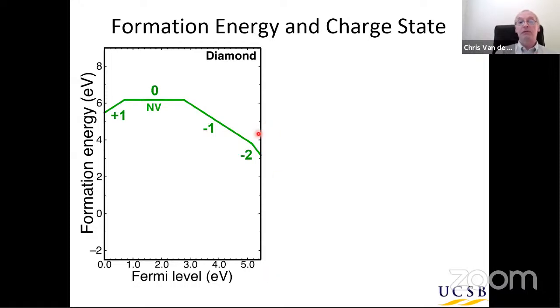And very often we use diagrams as the one illustrated here to investigate these issues. What is plotted here is the so-called formation energy of a defect, how much energy it costs to, for instance, create this NV center in a diamond host. And it is plotted here as a function of the Fermi level in the material, the electron chemical potential, which ranges from the valence band at 0 to the conduction band at the value of the band gap of diamond.